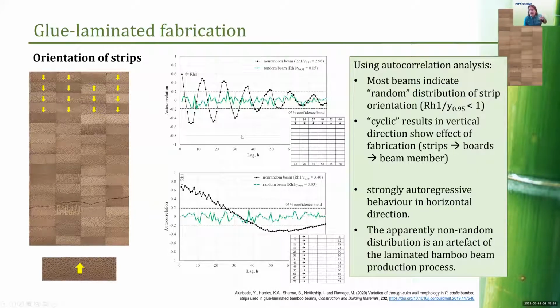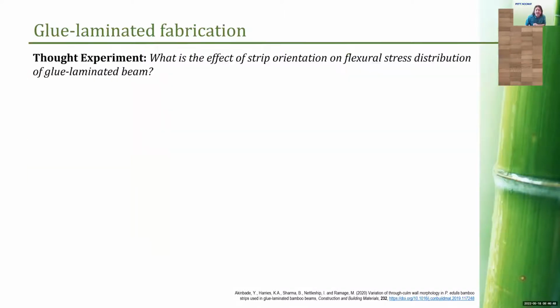In some cases, though, we saw a very cyclic distribution. So this black line on the top plot is actually representing the fact that the orientations of these strips are not randomly distributed in any way. And that's probably a function of how the fabrication went ahead, as how we went from the strips to, in this case, the vertical boards, and then laminating the vertical boards together into a beam member. And so analysis like this can help understand better the manufacturing process that we were talking about in the previous talk. And we looked at the same thing in both directions, both vertically and horizontally. And horizontally, again, we saw many, many random cases, but we also saw some strongly autoregressive behavior as well, as characterized by this particular case in the black line. And again, an artifact of the lamination process, or an artifact of the process that was used to fabricate these.